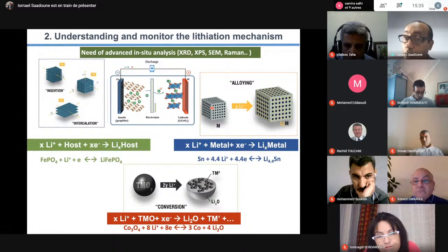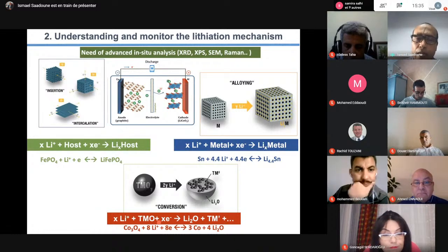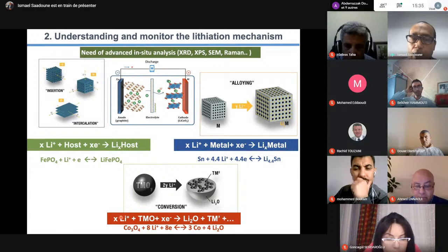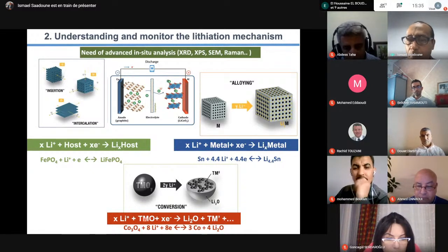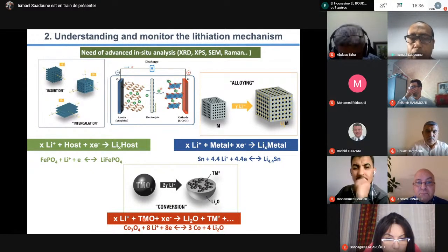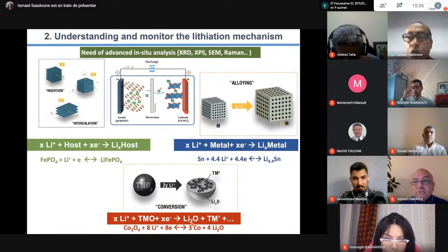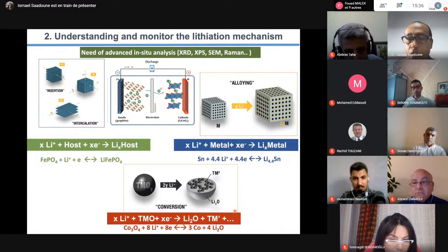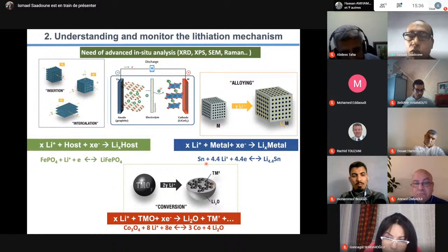The third mechanism is what we call the conversion mechanism. You start by some oxide, for example, from some NiO, and then when reacting with lithium, you form new materials, new species. So your starting material converts to new material. That's why we call it conversion.